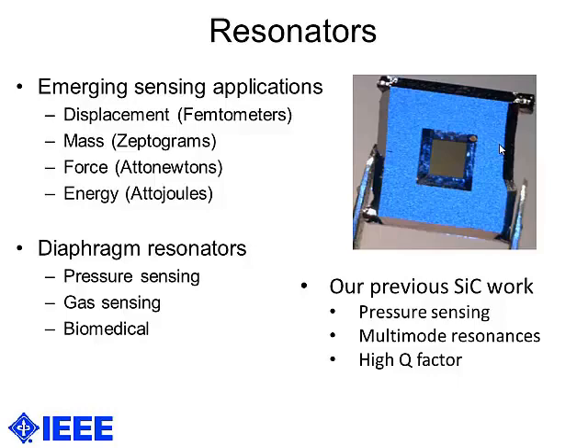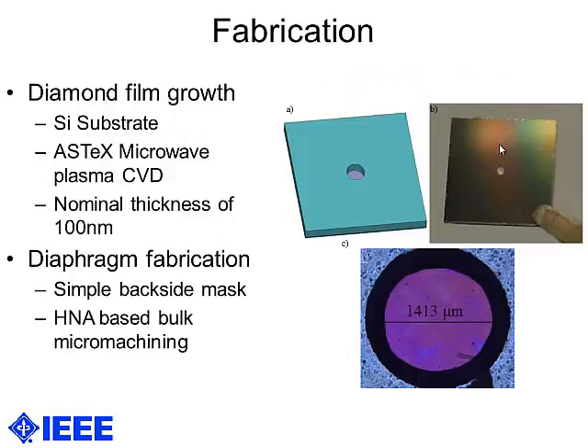Our previous work for silicon carbide, this is a polysilicon carbide resonator shown here. We've shown pressure sensing with multiple mode resonances with very high Q factors. Fabrication of these diamond membranes consists of a silicon substrate, then an ASTeX microwave plasma CVD system is used to deposit the diamond film on the silicon substrate to a nominal thickness of 100 nanometers.